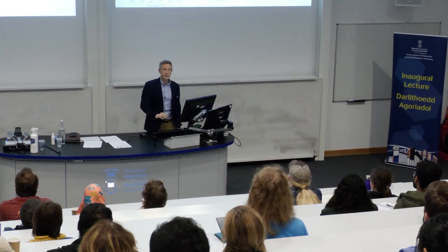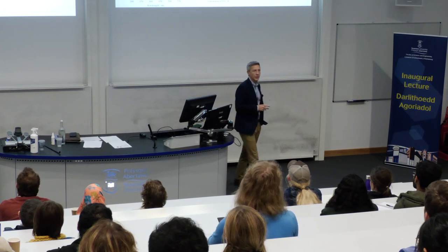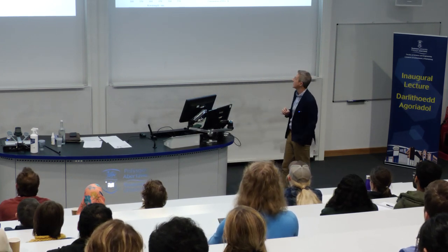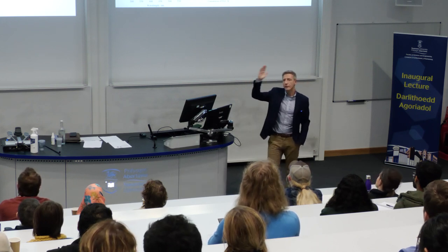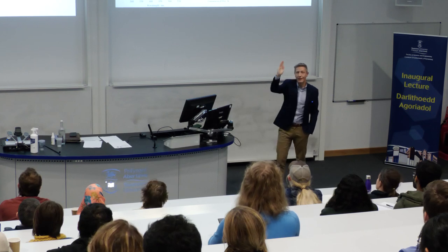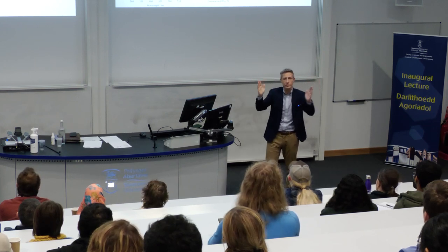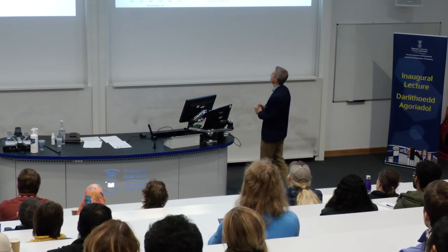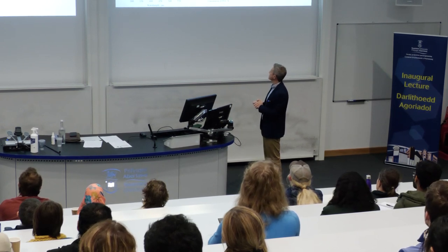We were also very much interested in understanding the photochemistry of these polymers. One of the problems and one of the things that holds these polymers back for use is the fact that they aggregate. So they're very planar, very flat molecules essentially. And when you increase the concentration of them, they all stack together. They tend to aggregate, and that quenches their light absorption and light emitting ability.